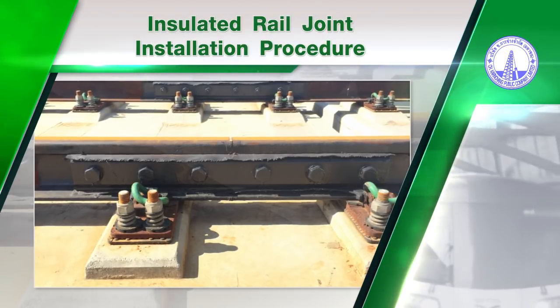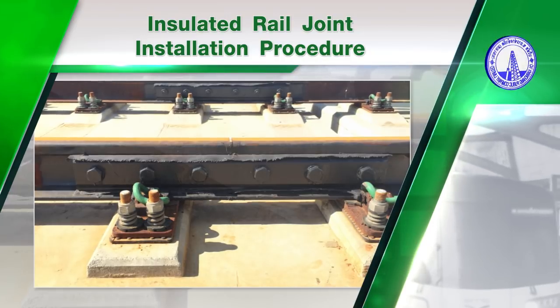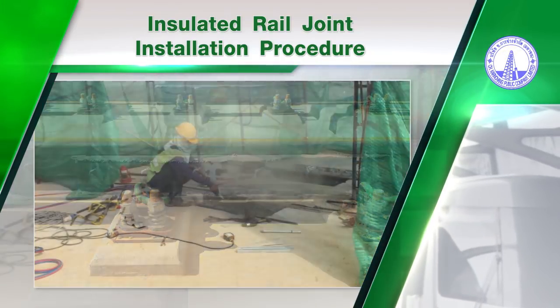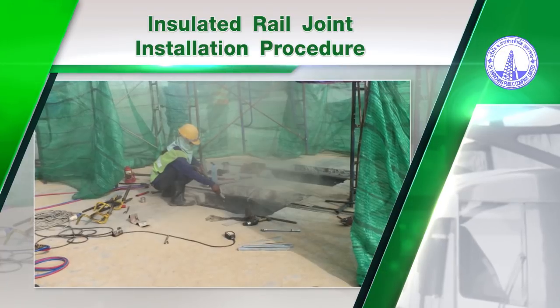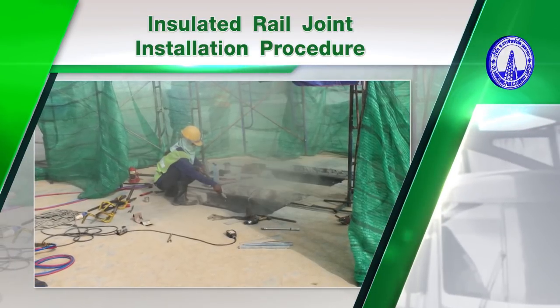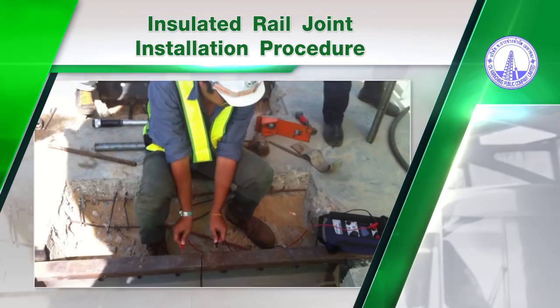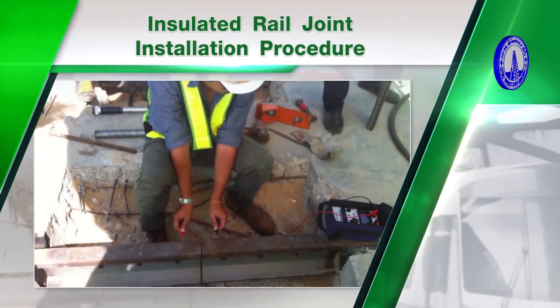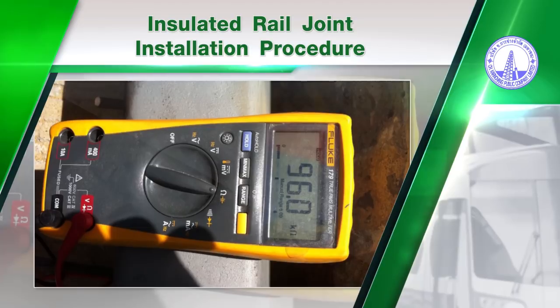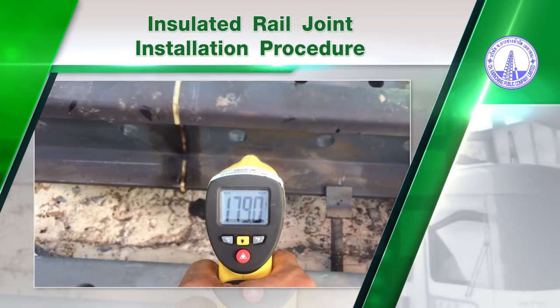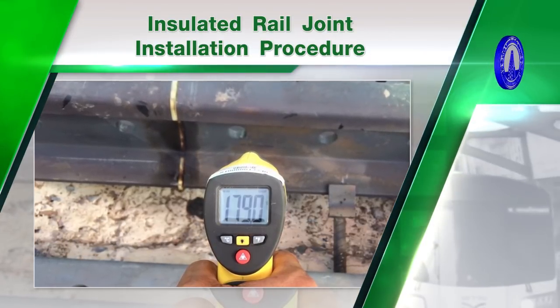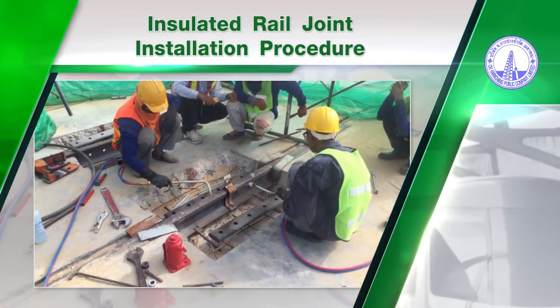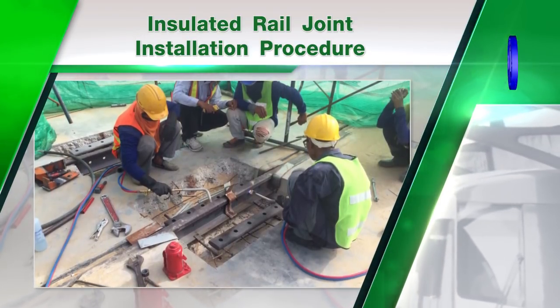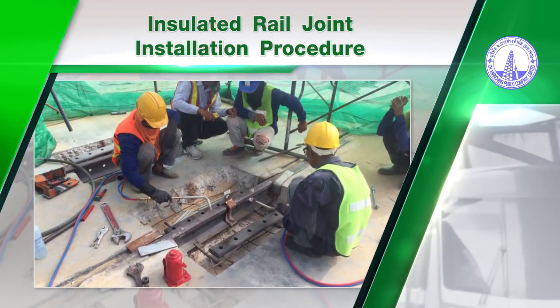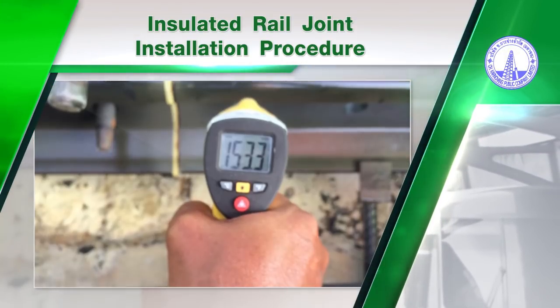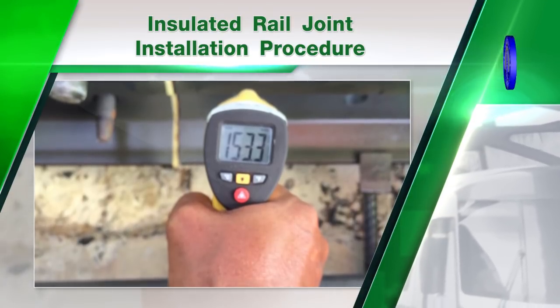Insulated rail joint installation procedure. 1. Grinding to clean the rail head and sandblasting it. 2. Measuring and recording pre-installation electrical resistance. 3. Installing end posts and adjusting track spacing and line in keeping with the specifications. 4. Heating the railhead to 155 to 160 degrees Celsius for the bonding agent to be the most effective and checking the temperature with an infrared thermometer.